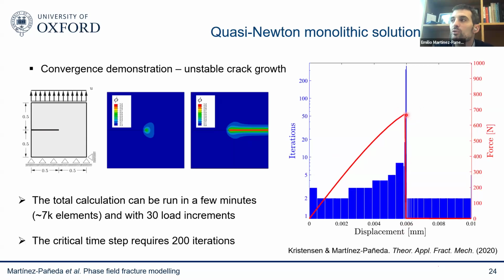But you can see that the phase field is able to actually predict not only the unstable crack growth, but even what happens after that crack has fully propagated. So it's very robust. And what you see here on the left, each of these bars is a load increment. I took 30 load increments. I could have taken 12, but I wanted to resolve more nicely this part here. And each of these is the number of iterations. You can see that initially convergence is pretty fast. And then funnily enough, when you are in this very critical load step, you need 200 iterations, which is quite a lot. Normally, you don't expect Newton methods to need more than 5 iterations. But here we converge after 200 iterations.